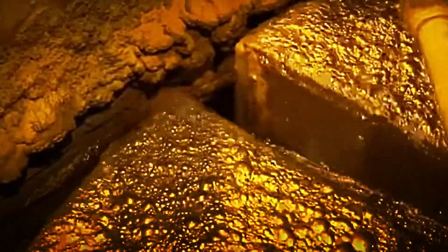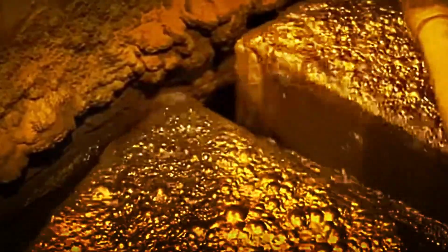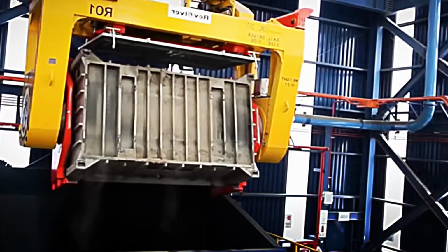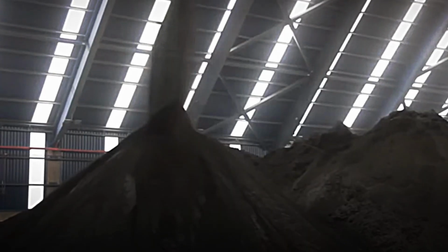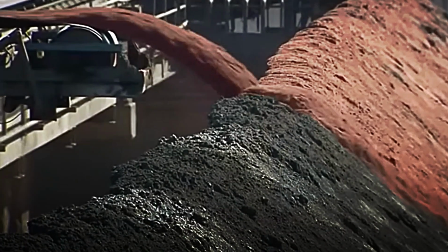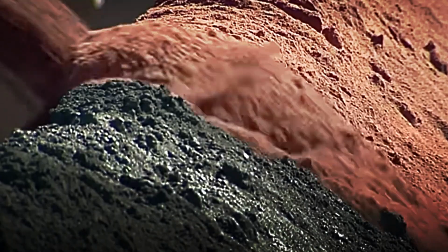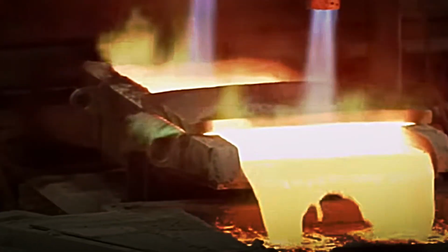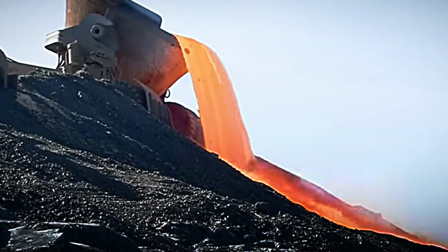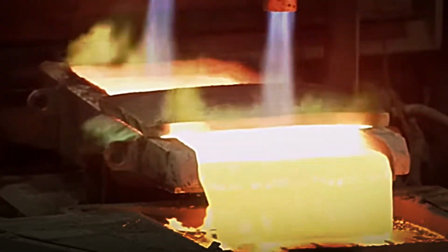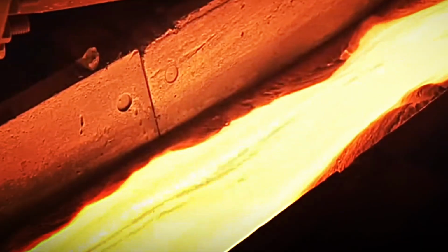There, it is mixed with silica sand, which acts as a flux, removing impurities. At extremely high temperatures, the material turns into a lustrous liquid. The slag containing iron and other compounds floats to the surface, while the liquid copper concentrates at the bottom with an initial purity of 60%. In a second furnace, the copper percentage rises to 98%. Giant cranes then transfer the molten metal to another furnace for final purification, achieving a purity of 99.4%.